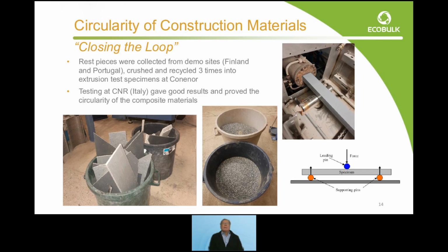And in this sense, we have realized a collection of the rest materials from the construction works, polyethylene based from Finland and polypropylene based from Portugal, delivered back to Conenor in our place. They were crushed and recycled again into extrusion test specimens at Conenor. And in this final loop, we can conclude that starting from the waste materials originally, some fractions become recycled up to three times. We produce test samples, as you see, the gray one coming out of the extruder die head, and these boards, which are hollow boards in dimension 60 by 40 and wall thickness 8 millimeters, have been tested by CNR in Italy, which gave good results and proved the circularity of these composite materials.